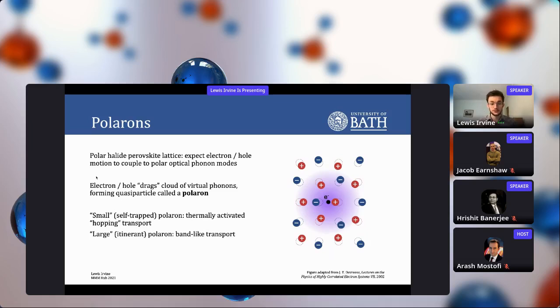And for clarity, there are two different types of polarons that tend to be talked about. There are small or self-trapped polarons. Those have thermally activated hopping transport. They're localized and they have this Arrhenius transport and a mobility that tends to go up as temperature goes up. But what we're going to talk about here is the large or itinerant polaron. That has much more band-like transport, so they behave a little bit more like free particles. In particular, they tend to have a mobility that goes down as temperature goes up. And that's what we see in halide perovskites. So that's what we're going to focus on.